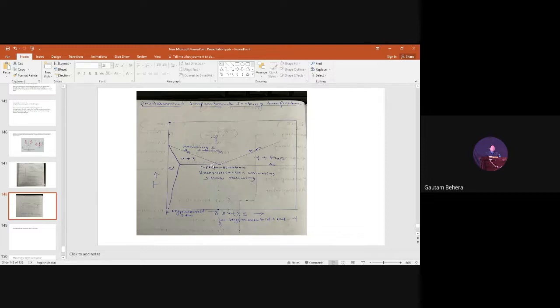So you have to remember that in these kinds of annealing processes, the rate of cooling is not so important. For this one, the rate of cooling is important because thermal stresses may be involved. But in these two cases, the rate of cooling is not so important, while in those cases it is very important. The rate of cooling will decide how the phase transformation will happen, to coarser, finer, or some other phases. Okay, I'll stop the class over here.